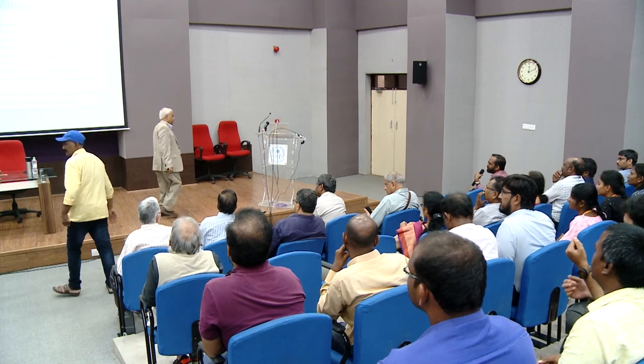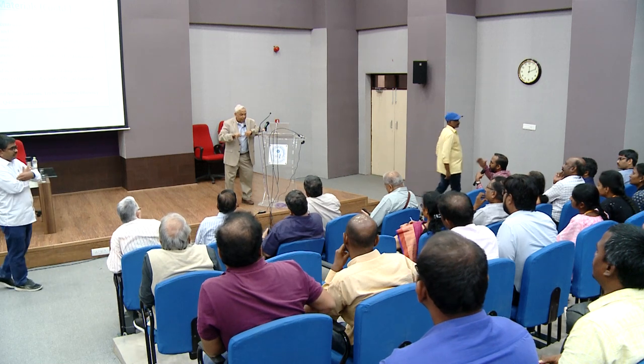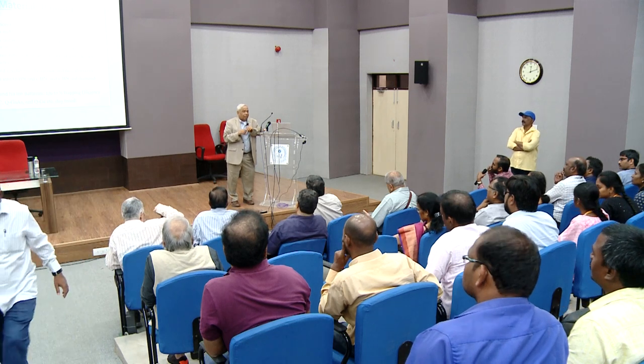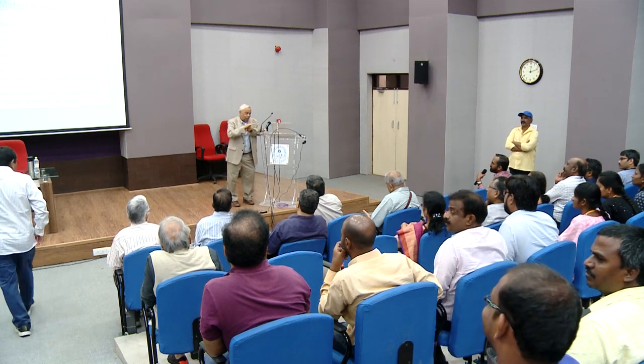Dr. Rajnikant: Sir, regarding Q-silicon ferromagnetism, when you talked about ferromagnetism, I saw that the saturation field is around 5,000 oersteds. But when you remove the magnetic field, the remanence is very low. So how do we go for applications where we want to use ferromagnetic materials? Yes, saturation is around 5,000 oersteds, and the moment you reduce the field below 5,000, the magnetization drops. That characteristic you can control by controlling the structure. So you can get higher values by controlling the atomic structure.